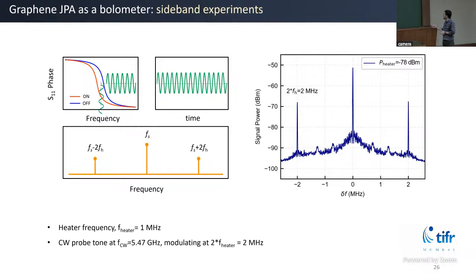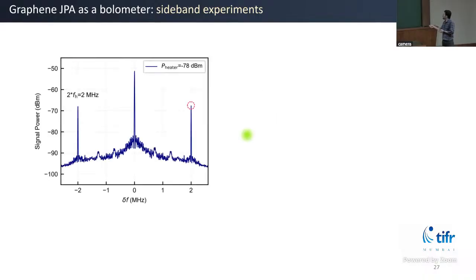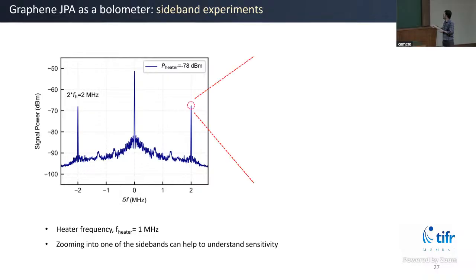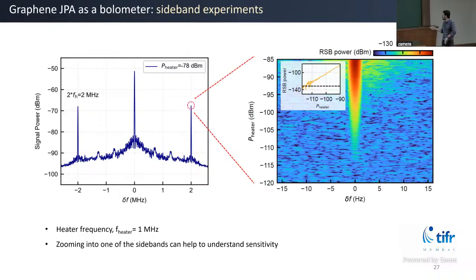And next, we use this sideband as our marker for the sensitivity of the device. We zoom in to one of the sidebands and try to resolve it as a function of heater power. When there is no heating, you don't expect any sideband. In this color plot, this red growing thing is the amplitude of the sideband. So when there is no heating, no signal is there. But when you start to increase your heater power, the sideband signal rises. So you can say that my bolometer can sense powers starting from these points, where you can see some signal in this 2D plot.